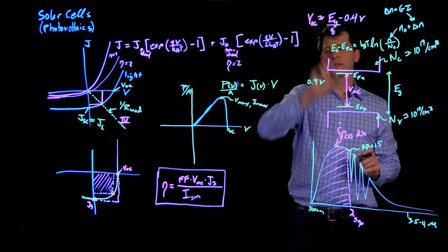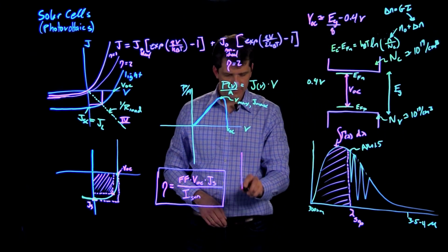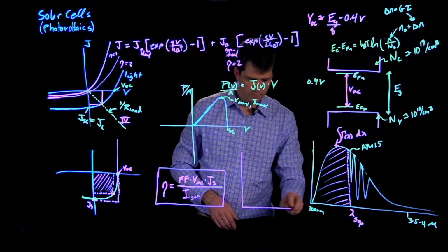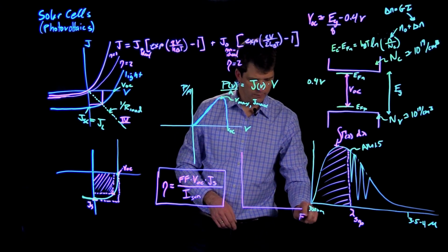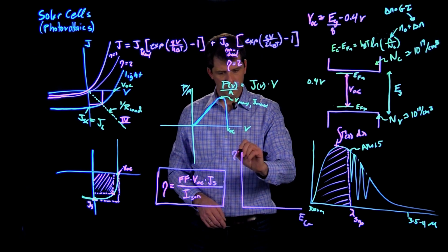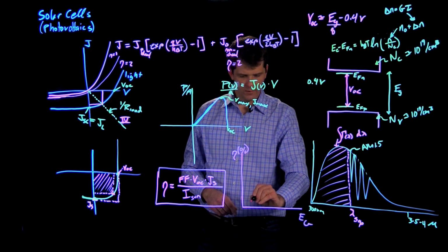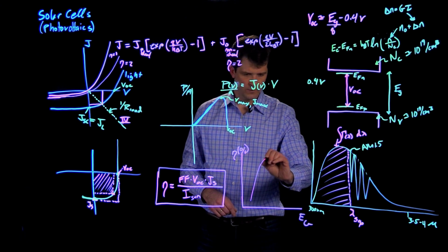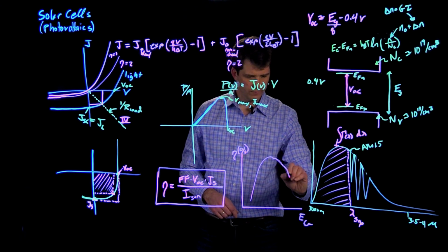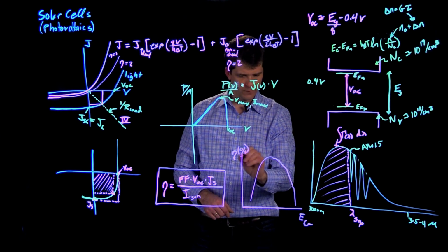And so you have linear proportionality here. Therefore, the maximum efficiency for photovoltaics can be argued to be a function of band gap, and it looks sort of like an upside-down parabola with some wiggles and details due to these holes in the spectrum.